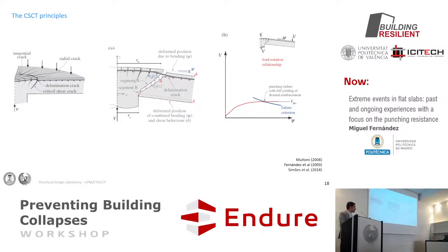And this happens not only when we have yielding, but also with more compact slabs, where we could have this punching when we have some partial bending yielding of the flexural reinforcement, or even no yielding at all. So this might be very brittle before any reinforcement yields, or when they are partially yielded, we can find a state of demand and capacity that match.